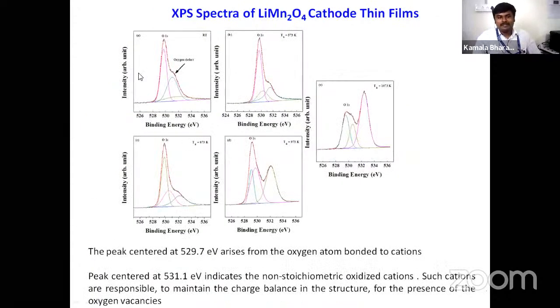To confirm that, we have carried out the XPS measurement, and this is the XPS spectra of oxygen atom. So the peak centered at 529.7 corresponds to the oxygen atom bonded in a cation, whereas you have a small hump at a little higher energy, which indicates the non-stoichiometric oxidized cations.